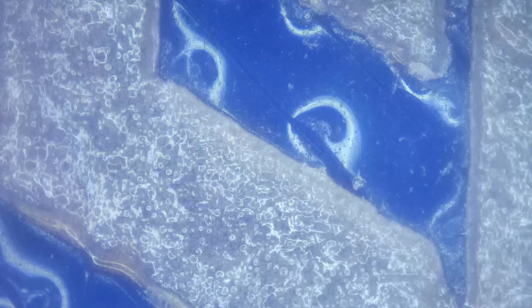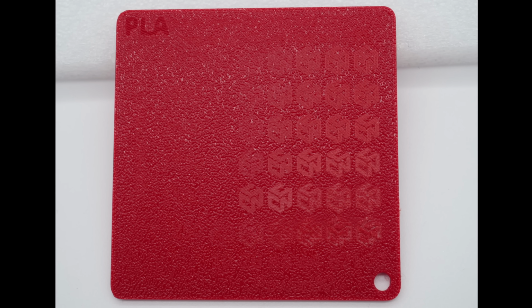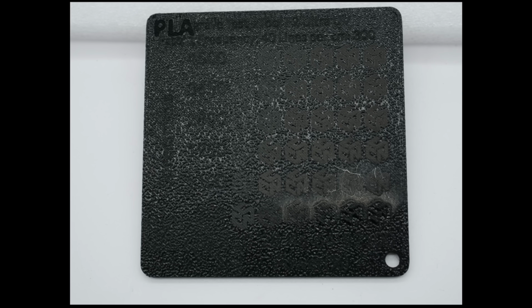Under the microscope, the UV marked samples were fascinating. If I didn't go overboard with the energy input, the material usually didn't look burned or charred like a wood engraving. The surface often stayed surprisingly intact, and the contrast seems to come from a combination of microfoaming and changes or removal of the pigment. Some colors like blue turned almost white in the marked areas. The only material I really had problems with were the red samples and some of the dark carbon fiber materials.